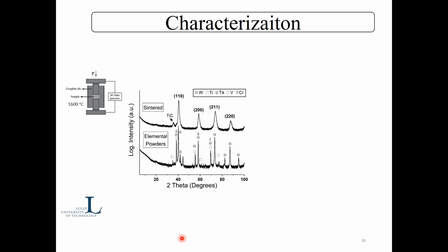So they are designed on the basis of the high entropy concept. We did spark plasma sintering to consolidate these materials. So they were consolidated, and you can see that when we have elemental powders, we get signals from the alloying elements like tungsten, titanium, tantalum, vanadium, and chromium. And after consolidation, we get a single solid solution. This means we have made an alloy of this high entropy alloy.